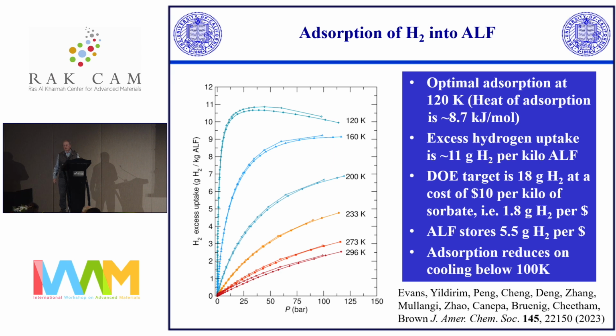So we get 5.5 grams of hydrogen per dollar, whereas the DOE target is 1.8. So we're about 3 times better than the target. So the beauty of ALF is you don't have to have the best performance for these large-scale things because it's so cheap. If we're reasonably good, nearly as good as the others, then the chances of anybody making a cheaper MOF than ALF is going to be vanishingly small.